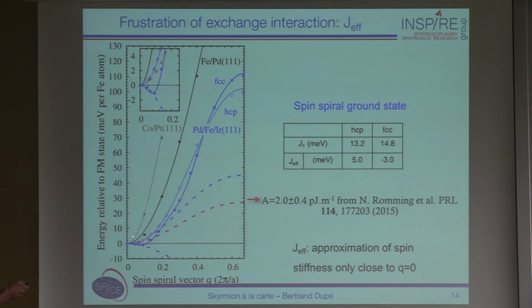So you see that close to the gamma point, the agreement is actually very good. But far from the gamma point, close to the edge of the Brillouin zone, there is a large difference. And so the idea was to look: is it actually physical? Does it have any consequence? And how to quantify that? How to quantify what we call frustration?